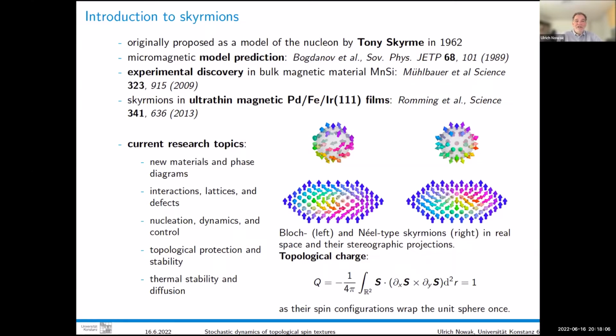So there are certain structures that you cannot reach by a continuous transformation. That's exactly the case for a skyrmion. So a skyrmion is a structure that you cannot unwind back to its original ground state. So if you look at this structure, you could say, okay, the ground state is blue. Everything pointing upwards. So can I grab this spin, the yellow one, and rotate it back in the blue direction without destroying the order? And you cannot, that's the point, because you would have to make a decision in what direction will I rotate it, let's say in the red one.